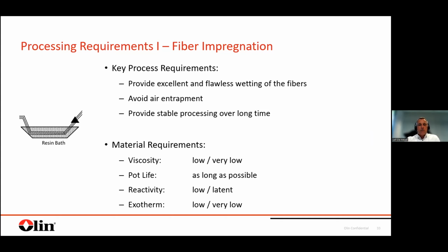Looking at the pot life, in particular for the classical open bath, it should be as long as possible. Or let's put it a little bit differently, as long as needed. If you have a process and you are able to run it with a very small bath volume, you may be able to accept some compromises on pot life, but in general, what we still mostly see is relatively big resin bath volumes. So basically, you need this entire volume of the material not to react and to keep the pot life and workability over a very long time. So reactivity should be low or even latent. And of course, you also don't want to have any reactions that are causing exotherms at this step. We're going to use more or less the same scheme for evaluation for all the different process steps.